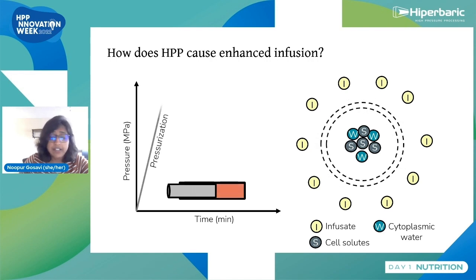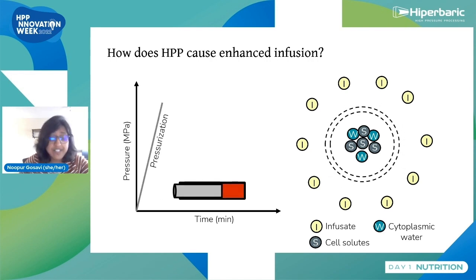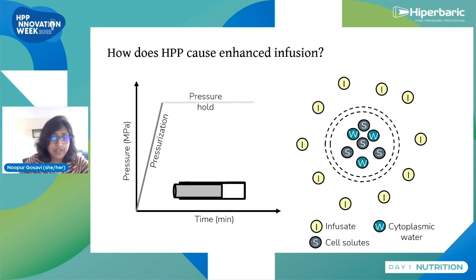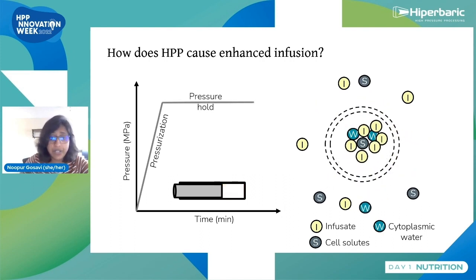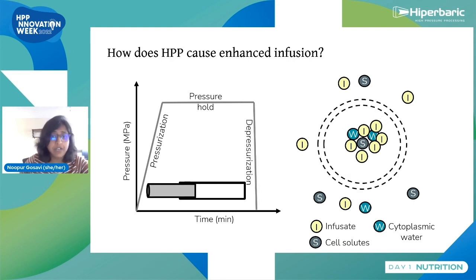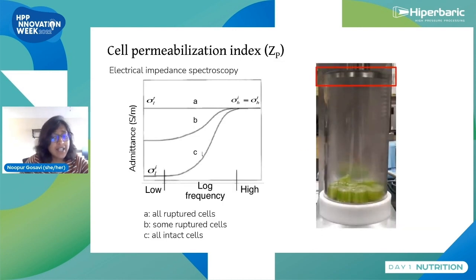So as we are increasing the pressure, the cell wall of the food matrix permeabilizes. That means it breaks, and that reduces the resistance. So when you're holding the pressure, now the infused molecules can move in and out of the matrix. So when we release the pressure, we end up with a cell that is enriched in the amount of infusion. So it is important that we are able to quantify the cell breakage. So what we do is we pass a high electrical current over a range of frequencies through these food matrices and measure the level of cell breakage, which is also quantified as a cell permeabilization index, which is ZP.